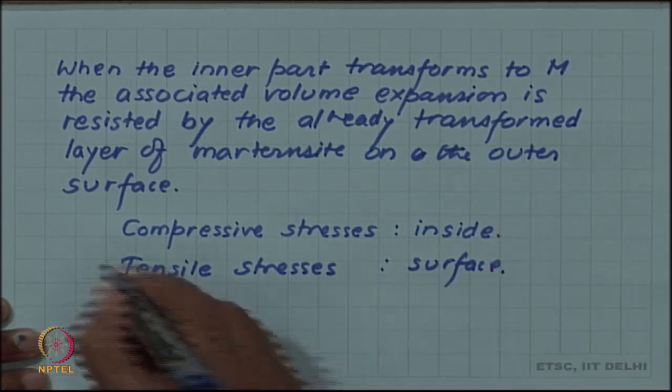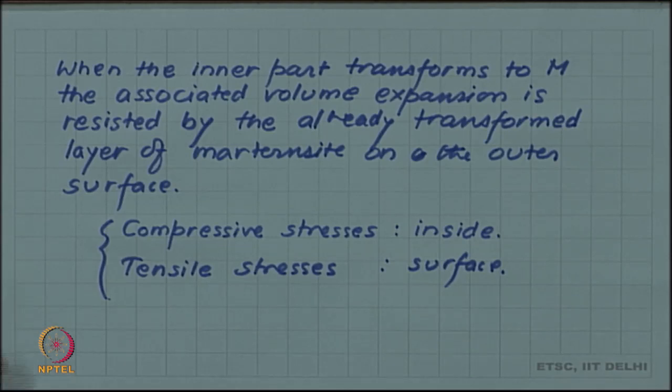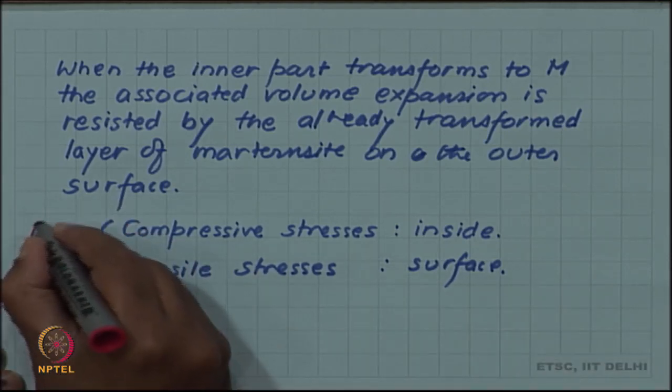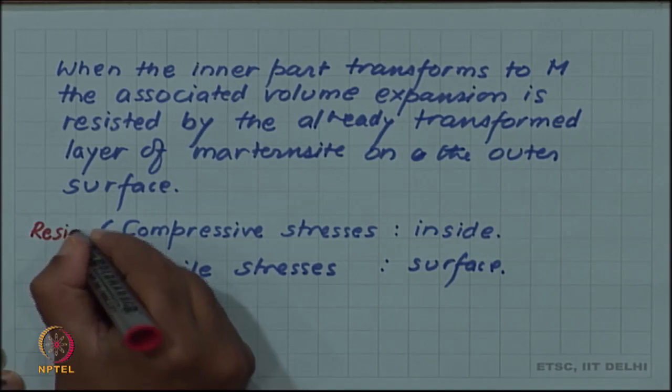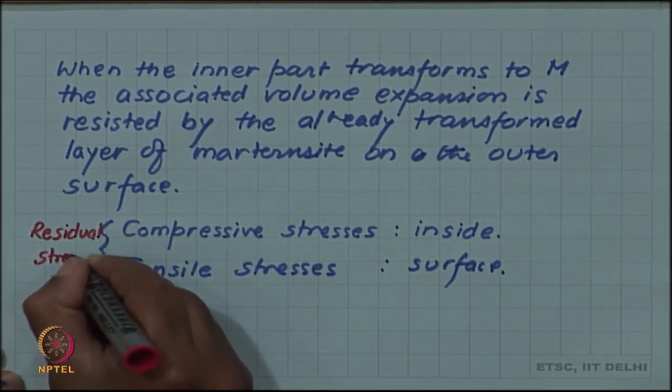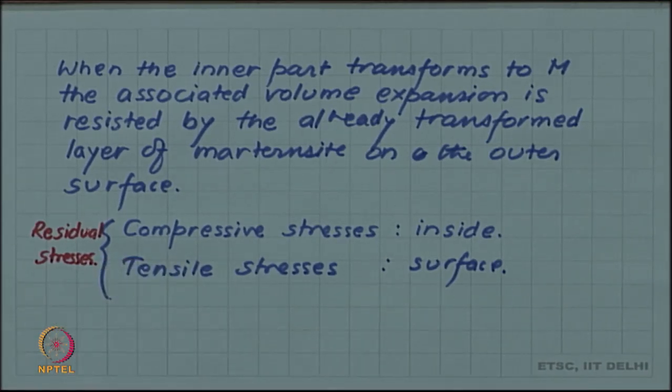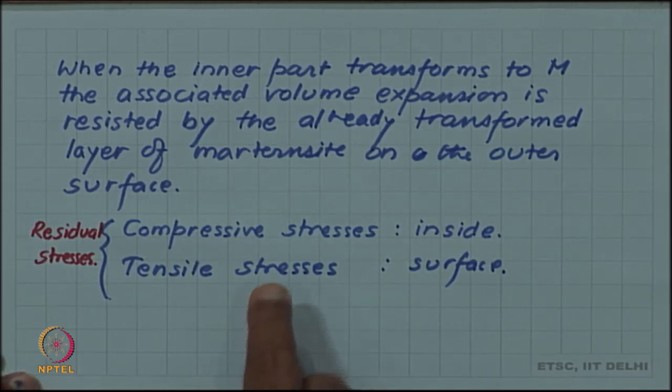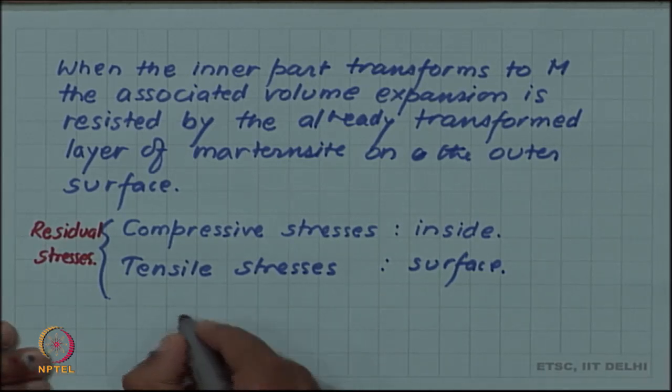These stresses are called the residual stresses because we are not applying any external force to generate these stresses, and in particular tensile stresses are quite dangerous because they lead to cracking. And these tensile stresses you can see are there in the hard and brittle martensite layer. So the tensile stresses on the surface martensite can lead to cracking which is called quench crack.